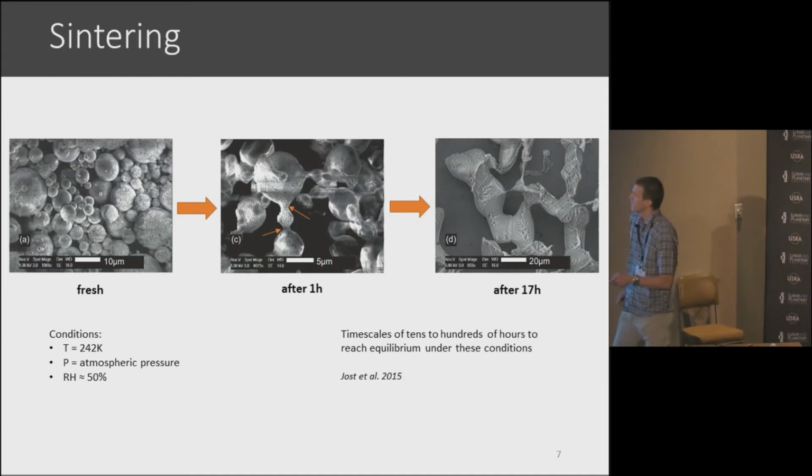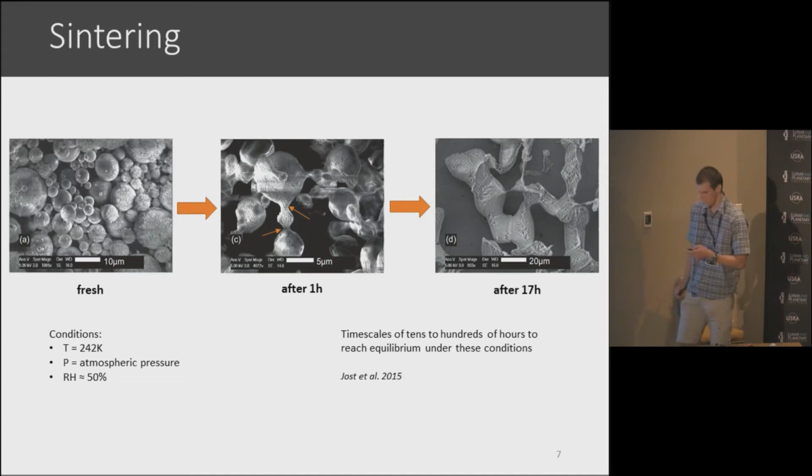What we see as well is that here the surface is really smooth, and it seems that material sublimates from the surface, condenses in the neck region, and creates this very irregular honeycomb-like structure on the surface of the particles.